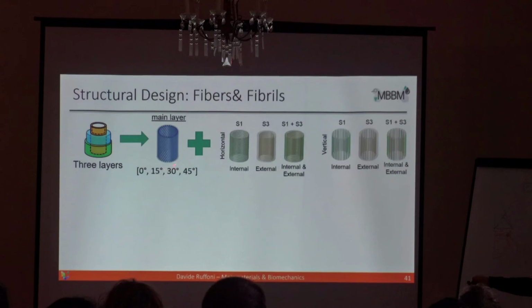vertical, 15 degrees, 30 degrees or 45 degrees. This is the main layer, and then to reinforce this main layer with either horizontal, what we call fibrils because they are smaller, on the outside, on the inside, or on both layers and on both regions, and also vertical on the internal, external, or both.